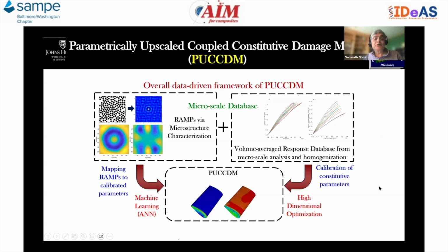So up to that point was a micromechanical model. Now we are going to develop the upscale model, the PUCCDM. For that we need the identification of the RAMPs from microstructural characterization. We need to establish the volume average response database from microscale analysis followed by homogenization. And then we need to use machine learning, using these two data together with the thermodynamical framework, to map the RAMPs to the calibrated parameters.